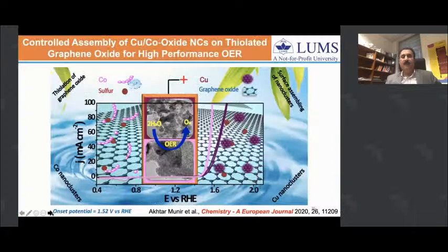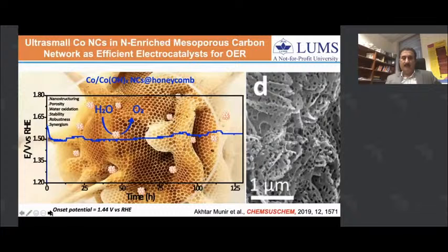Apart from this, very recently we also coated graphene oxide nanoparticles with copper and cobalt oxide nanoclusters and self-assembled them into small chain-like structures on the graphene. We found that they are really very stable, highly stable catalysts which can work under extremely alkaline conditions to produce oxygen gas from water by splitting water.